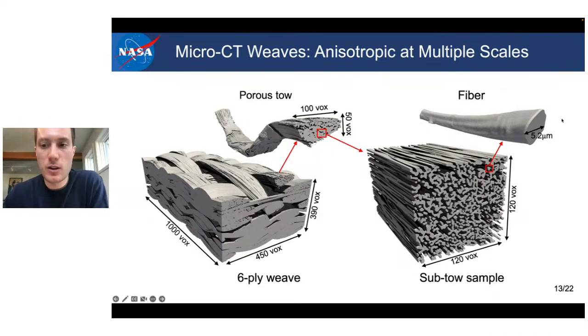these materials. And actually, through a research of ours, we've recently discovered that we can track this anisotropy also all the way down to the fiber level, and these fibers are basically made of cylindrical graphene sheets, and so of course along the fibers there will be a lot higher conductivity, for example, than across it. And we basically researched this behavior, and we could see that it matched experiments. We could match experiments only by imposing this different fiber conductivity.